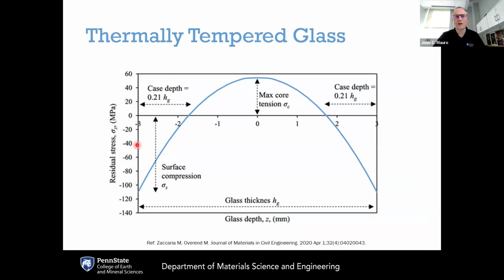This is what a typical stress profile looks like for thermally tempered glass, where you can see there's surface compression on the exterior surfaces. So this is on the order of 100 megapascals of compressive stress at the surface. If you integrate all the compressive stress at these two surfaces, those integrated areas add up to match the integrated tensile stress in the interior. So all of the stored tensile energy here in the interior has to match that of the compression on the surfaces. Two of the key properties here are what is the magnitude of the compressive stress at the surface? Higher would be better. And also, what is the depth of the compressive stress layer? Basically, you're safe as long as the cracks do not penetrate through the compressive layer to get through this depth of layer and into the tensile layer.